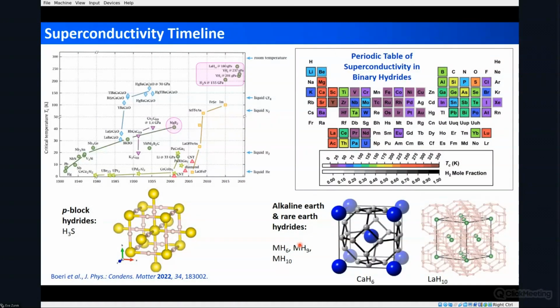So what we note, though, is that the electropositive elements, when they do have very high TCs, assume one of these types of structures, whereas when you have a p group element, the chemical bonding is quite different. Here we see that the sulfur forms a multicentered bond with hydrogen, where the hydrogen kind of bridges these two sulfur atoms. That would obviously not happen without pressure. And in these types of systems, we see hydrogen forms bonds with other hydrogen atoms, and there is only kind of an ionic interaction with the electropositive element.